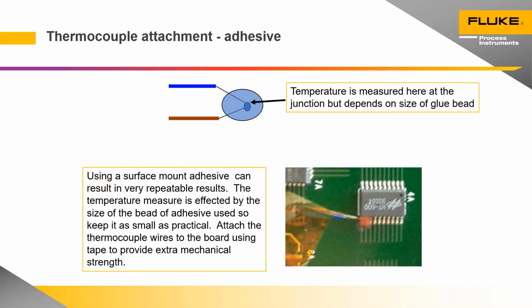In this particular image, you will spot that I was very clumsy and that the two wires are crossing each other before they even get to the component. So I'm likely to be measuring the temperature about 15 millimeters or 10 millimeters to the left of that component. So this is going to measure air temperature. I think you can just see that here. It's likely those two wires are touching, and that's where I'm going to be measuring temperature in this particular case. So take care.